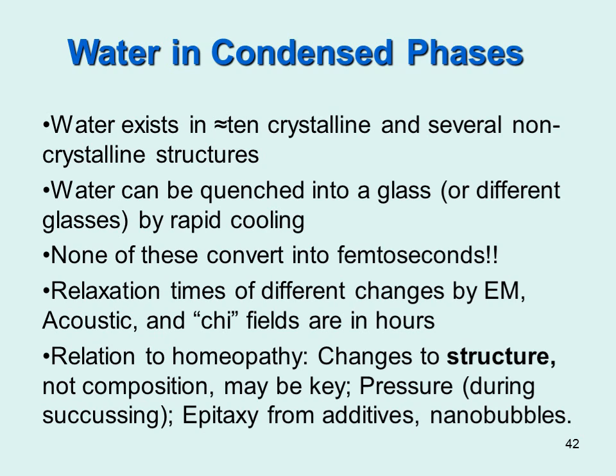Now, water itself, in its condensed phases, what about its structure? What do we know about it? First, water does exist in at least 10 crystalline and several non-crystalline structures. So there's no ifs, ands or buts about it. It's normal. Water can be quenched to a glass just by dropping it into liquid nitrogen, not a big deal. And I should say, for those who muddle this up with the femtosecond relaxation times of bonds, there's nothing to do with that. These are phases which stand side by side for days and weeks and years, and so on, under the right PT conditions.